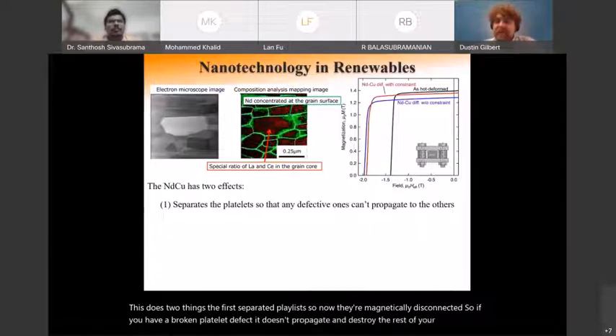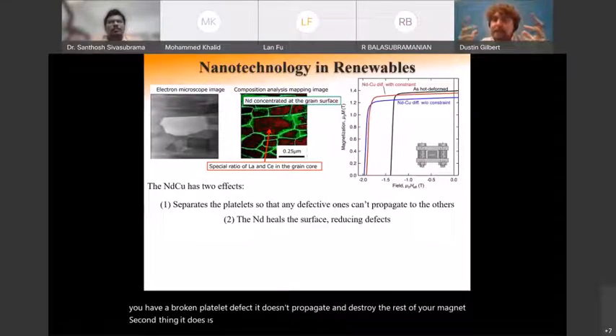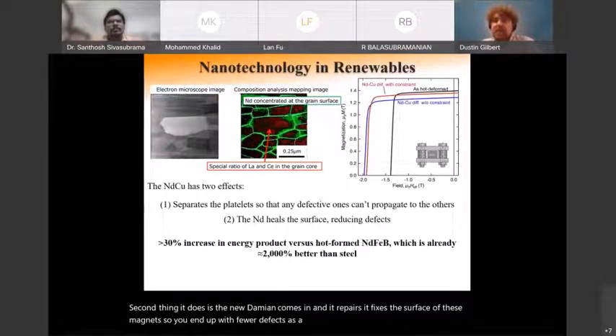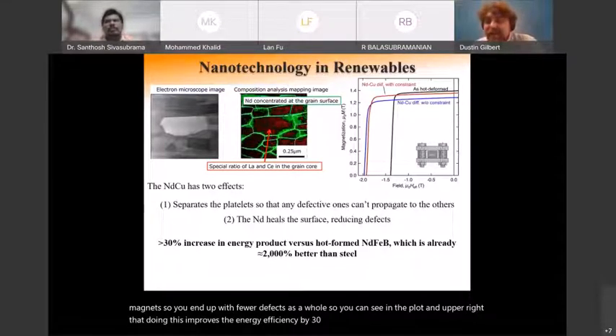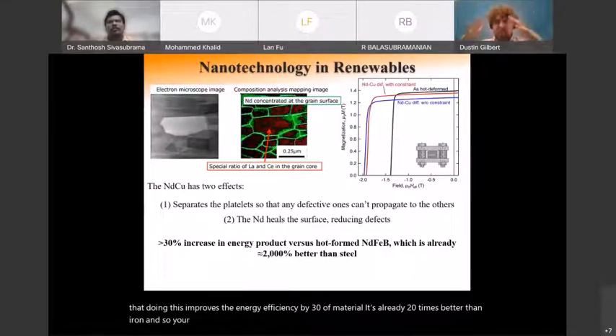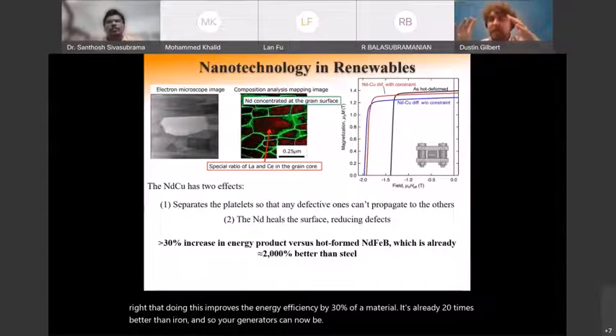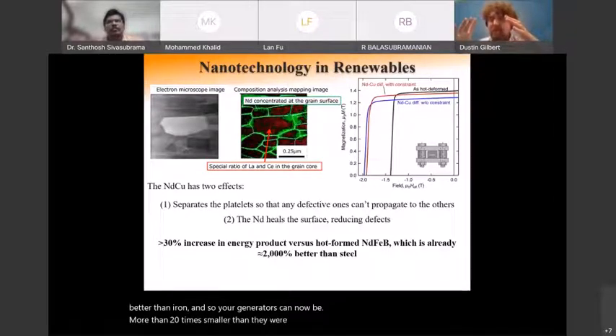Second thing it does is the neodymium comes in and it repairs, it fixes the surface of these magnets. So you end up with fewer defects as a whole. So you can see in the plot in the upper right that doing this improves the energy efficiency by 30% of a material that's already 20 times better than iron. And so your generators can now be more than 20 times smaller than they were in just 30 years ago.